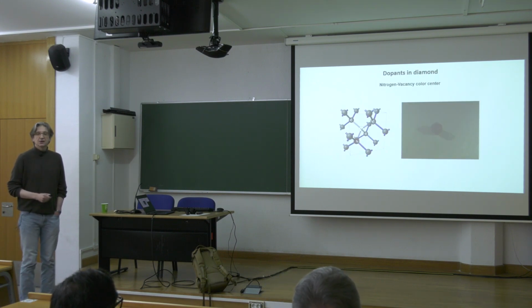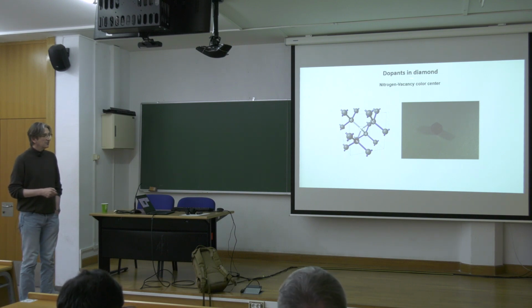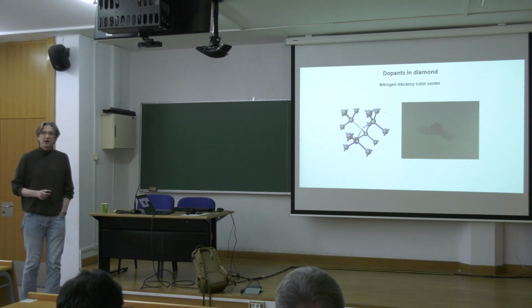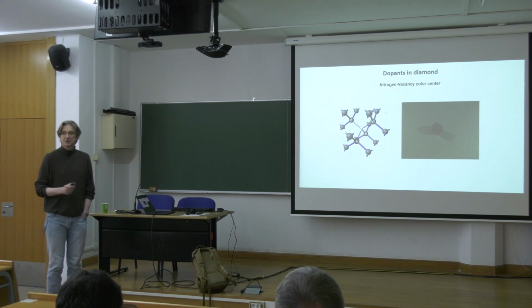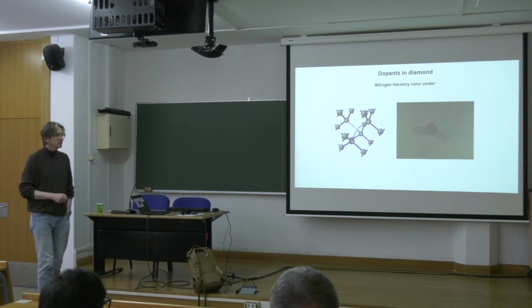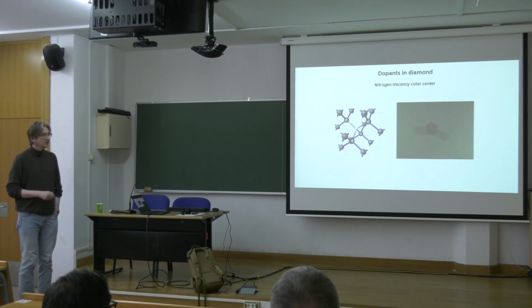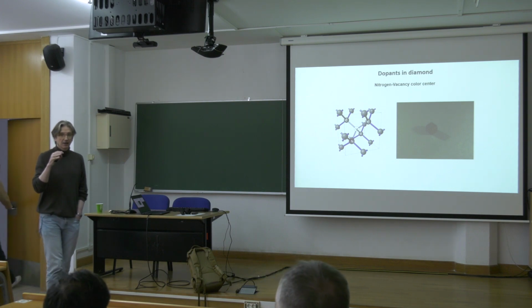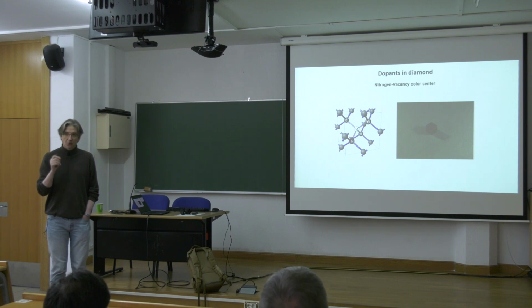The system, the qubit that we are using, is the nitrogen vacancy color center in diamond. Actually, there are hundreds of known dopants in diamond which are optically active, but this nitrogen vacancy color center attracted attention because it combines several very interesting, very promising spin and optical properties. In structure, it consists of nitrogen sitting at a lattice position plus a vacancy nearby. And this vacancy in diamond is not really a vacuum. It means that there are some dangling bonds which are free. In total, this system has 4 dangling bond electrons, 1 additional electron from nitrogen, and 1 coming from an external donor to form a 6 electron system, like an artificial molecule in diamond, having a strong optical transition.